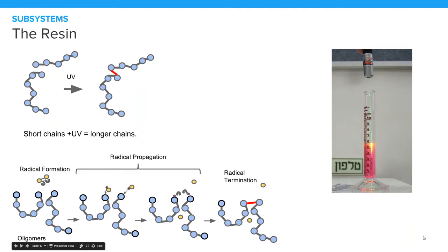During the polymerization process, we're zapping the resin with UV light. The light activates the photoinitiators. I already explained how they split apart. They send out free radicals into the system, and those cause the oligomers and monomers to be attracted to each other. There are two main variables when we design our resins. There's the energy of cure, which is the amount of laser energy required, and then the penetration depth, which is how far the laser can actually penetrate into the resin. You can see some of that testing for penetration depth on the far right. The energy of cure is controlled by the photoinitiator, while the penetration depth is controlled by blocker elements that we also suspend within the resin.